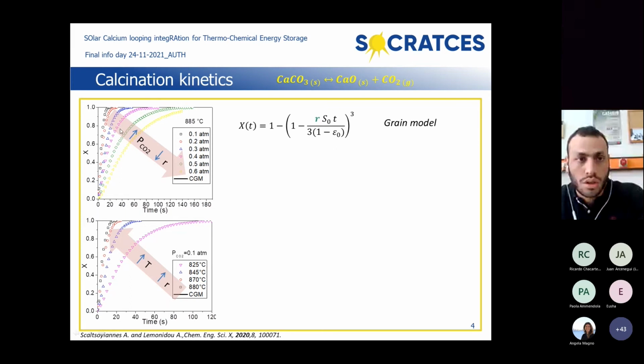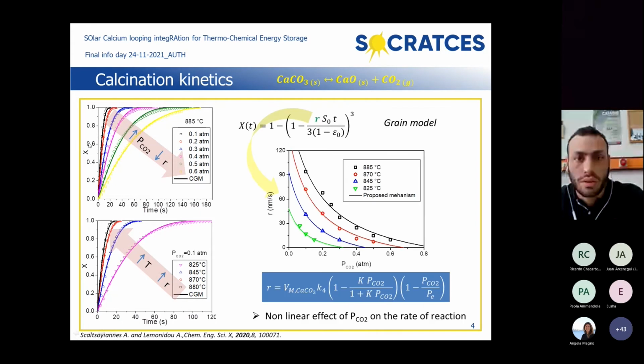So during modeling, we used the grain model where we introduced as input parameters the initial surface area and the porosity of the material from nitrogen porosimetry measurements. And after fitting this equation on each experimental conversion time curve, we derived the only fitting parameter, the specific rate of decomposition reaction. And as you can see, there is a non-linear effect of the CO2 partial pressure on this rate. And we use this Langmuir type equation to fit this dependence.